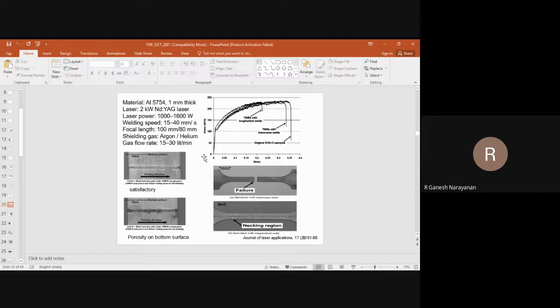Okay, so I will give you some examples. Again, the material is aluminum, 1 mm thick, taken as the raw material. Laser welding is used. Laser power between 1000 and 1600 watts has been used. Welding speed is changed, focal length is changed, shielding gas flow rate can be changed, and you can see the welded components nicely.